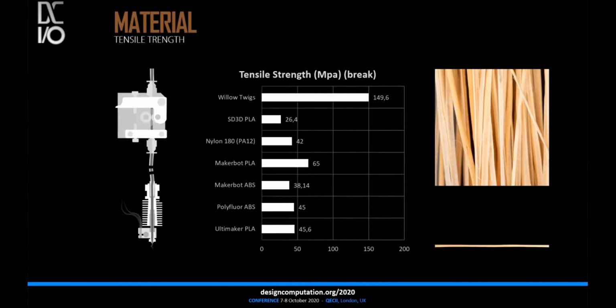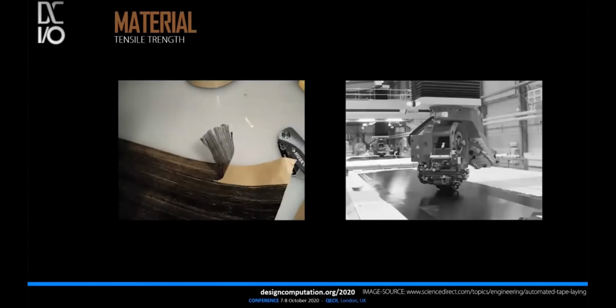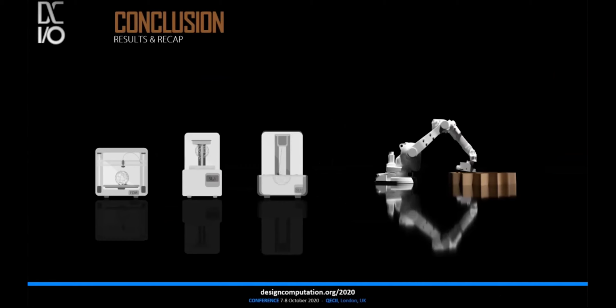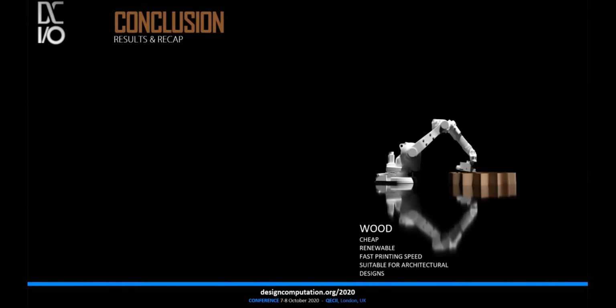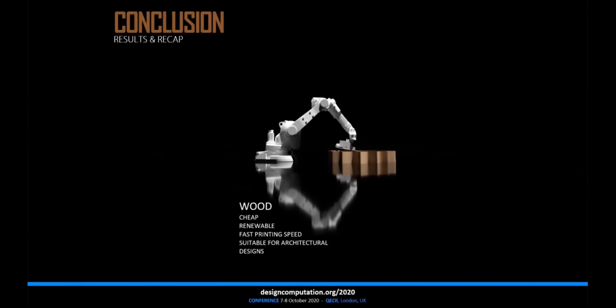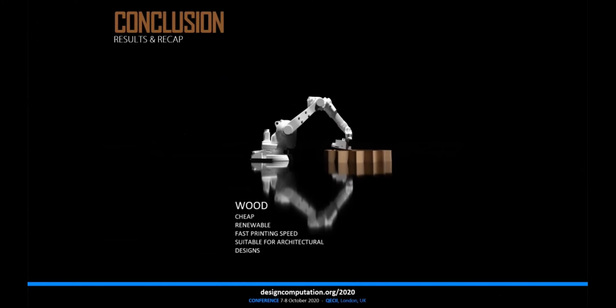The technique, however, is more related to automatic tape layering, but in an upright printing orientation. Both methods require a pre-laminated tape, in this case a treated willow twig that gets printed or layered. Due to the upright printing, this printing technique is in its results comparable to an FDM printing approach. The printing process shows various advantages in printing with combined willow twigs. For example, the overall printing speed compared to a traditionally used FDM and SLS 3-dimensional printing methods is improved by having a solid material and a larger filament profile.